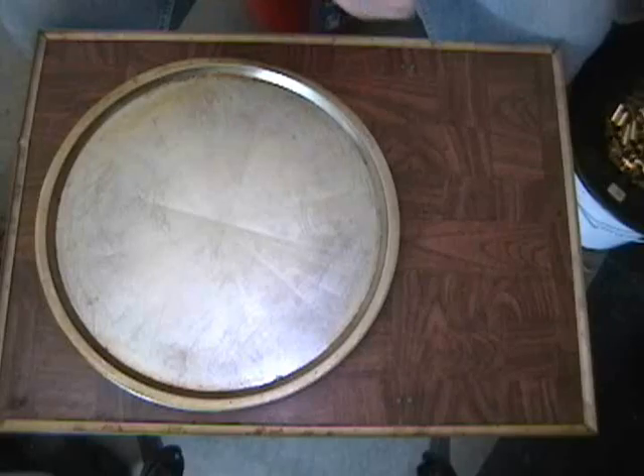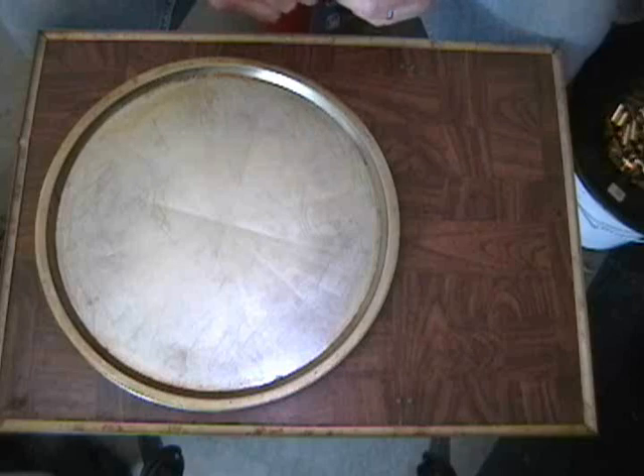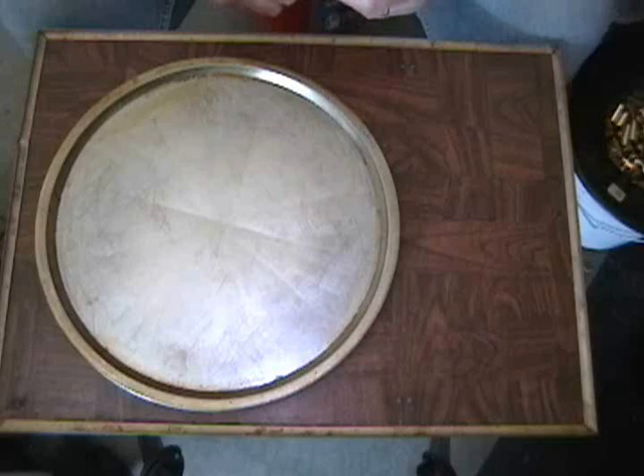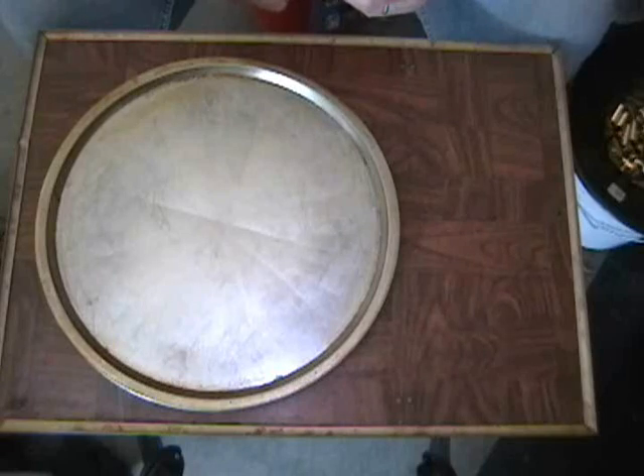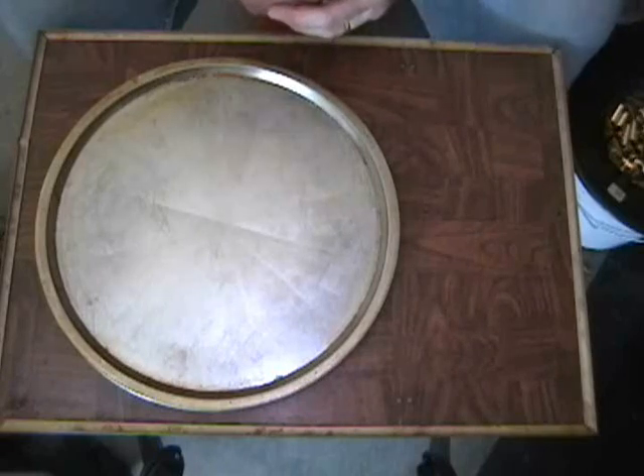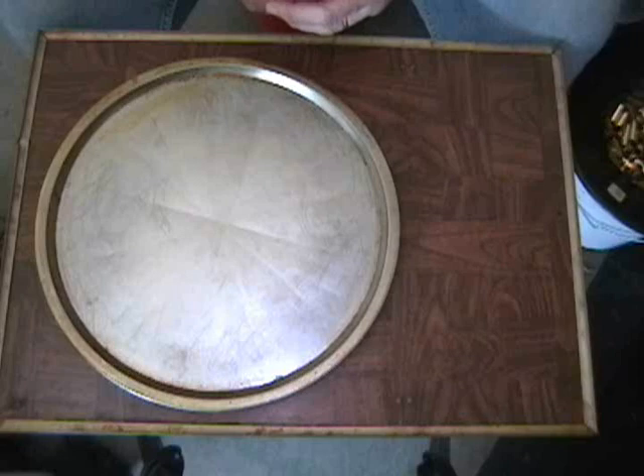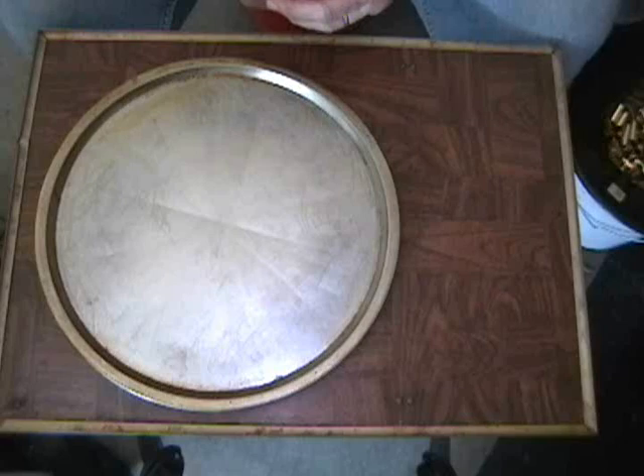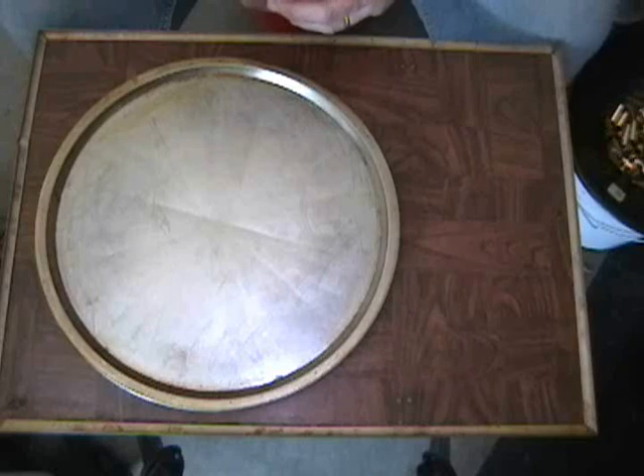The mouth of the 45 Colt, also called 45 Long Colt, cartridge case is particularly weak for some reason. It only takes 2 to 3 reloadings with standard pressure loads for a crack to develop at the case mouth. However, I've found over the years through experience that annealing the case mouth of the 45 Long Colt will extend the cartridge case life by twice at least, sometimes 3 or 4 times. I've gotten as many as 8, 10, or 12 reloadings of a single cartridge case that I have annealed every 3rd or 4th shot. So let's demonstrate that process.